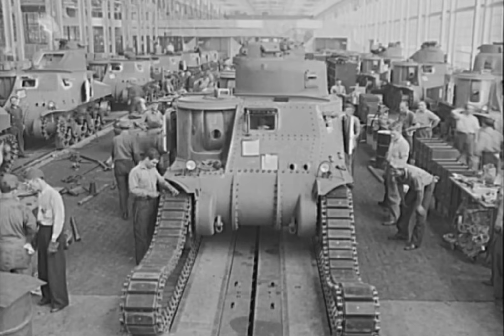Every plate underwent ballistic testing before shipment. Test facilities maintained batteries of German and American anti-tank guns that fired at sample plates cut from each production batch. If a plate failed ballistic requirements, the entire batch was rejected and returned to the mill for reprocessing. This ruthless quality control ensured consistent performance. American tank crews could trust that their armor would perform as specified. German tank crews enjoyed no such confidence by late 1944.